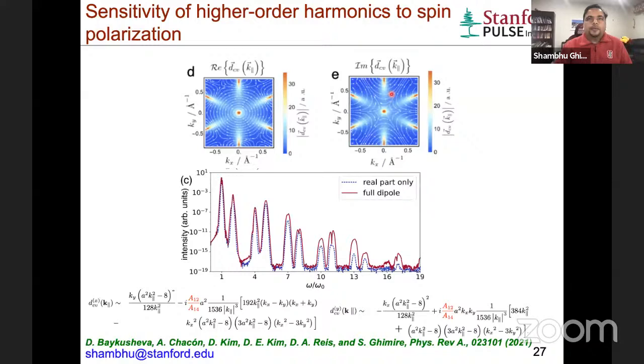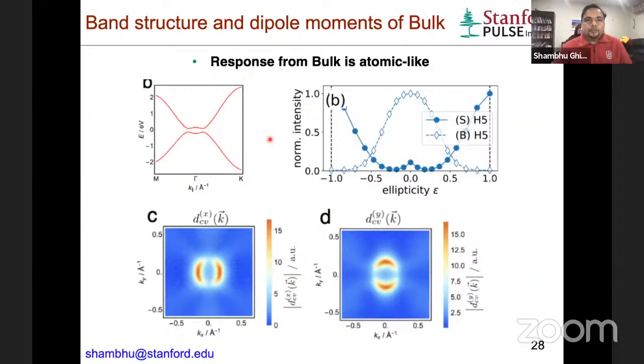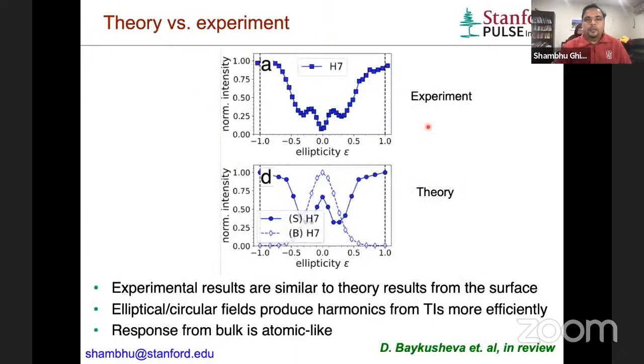So this is the unique feature of the topological surface states. You would not have these features in the bulk, right? For example, these are the bulk bands. They have a minima not at the zone center, slightly away, and they also don't have these vortex features in the transition dipoles. Clearly this is the signature of the topological surface states that gives rise to the enhancement for circular polarization. So this is the theory on the bottom, and a representative experimental measurement is shown on the top. You can see that the theory, especially the response from the surface states, more or less reproduces the experimental observation.